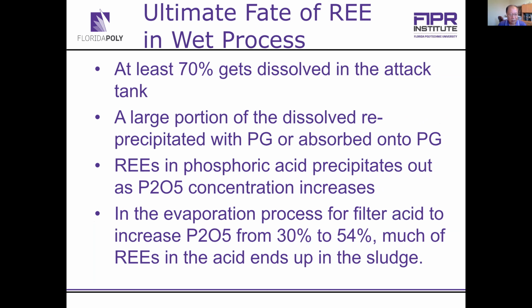So in the acidulation process, roughly 70% of the rare earth is actually dissolved in the acid tank. But a large portion got precipitated onto the phosphogypsum. And also, the rare earth in the phosphoric acid eventually ends up in the phosphoric acid sludge if evaporation is practiced. Some of the phosphoric acid plants have the evaporation process, some not. But if you have the two-stage evaporation, then most of the rare earth elements in the acid eventually report to the sludge. As we will discuss, that's the stream with the highest concentration of rare earth elements.